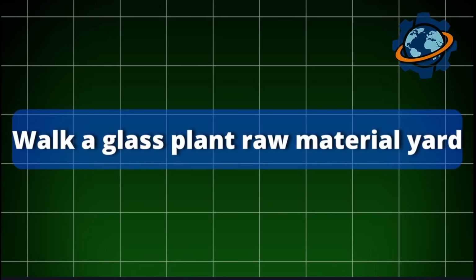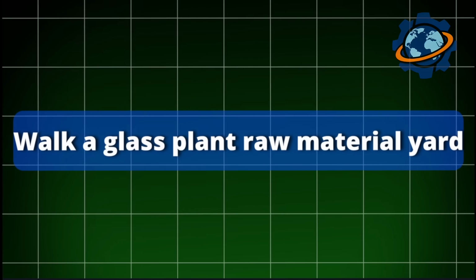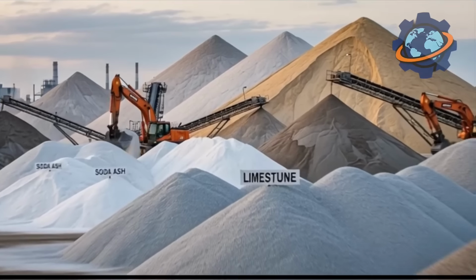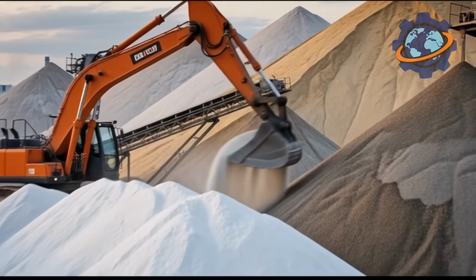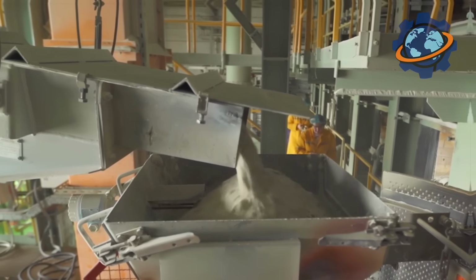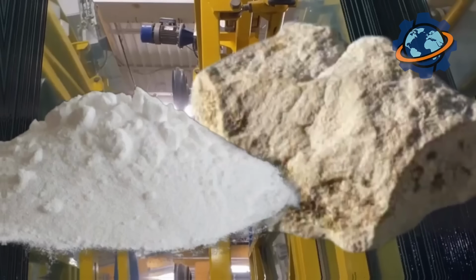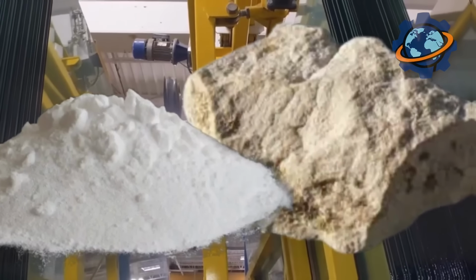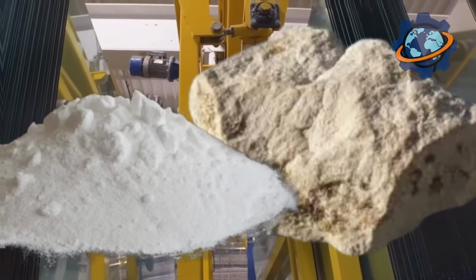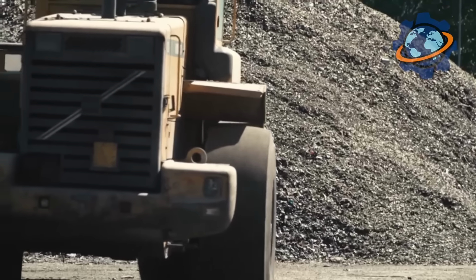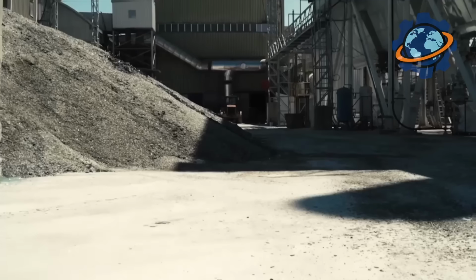Walk a glass plant raw material yard. Mountains of sand sit beside smaller piles of soda ash, limestone, and dolomite, the recipe unchanged for centuries. Automated systems measure ingredients to within grams per ton. One batch mixer explains, sand is the main ingredient, but the additives determine everything: melting temperature, strength, thermal expansion. Get ratios wrong and glass cracks cooling from the furnace or shatters at the first bump on the road.